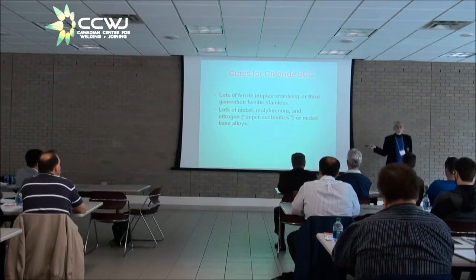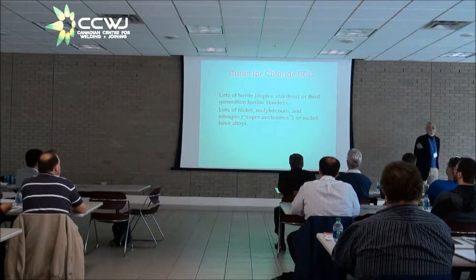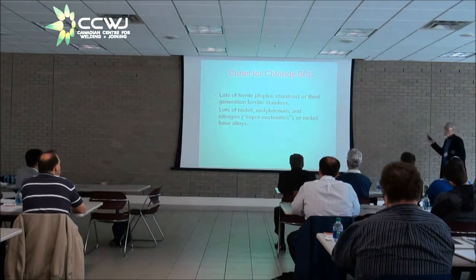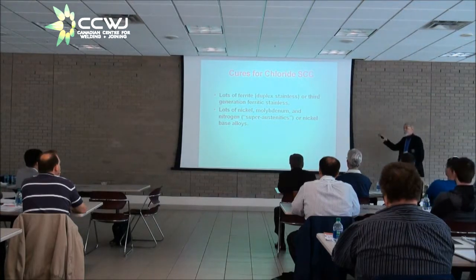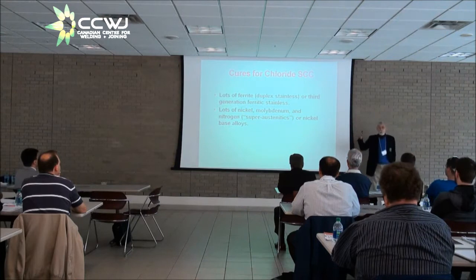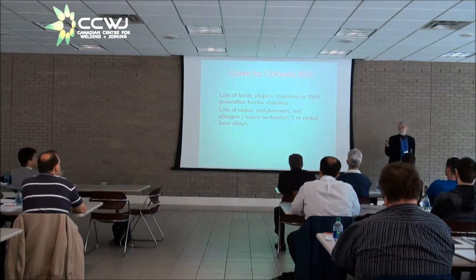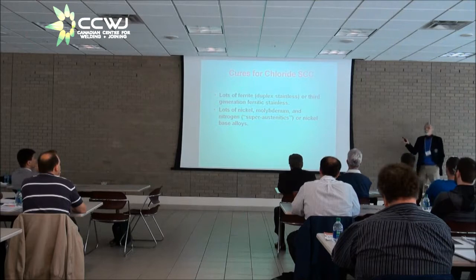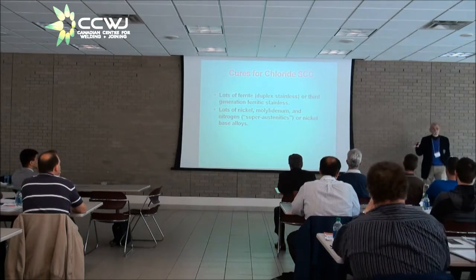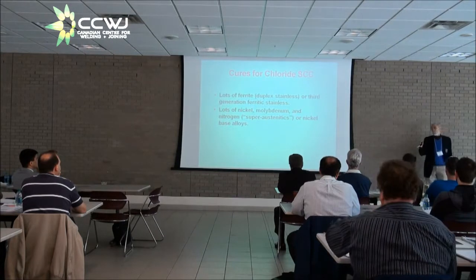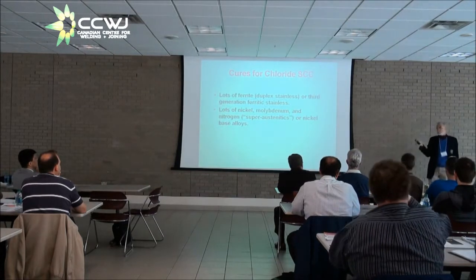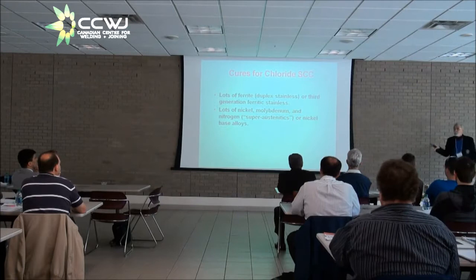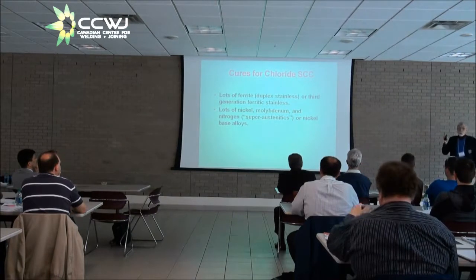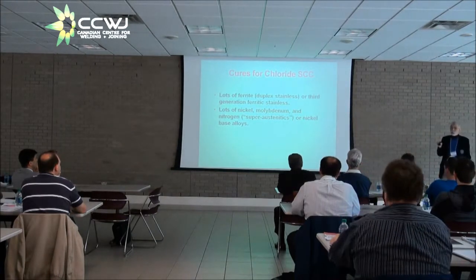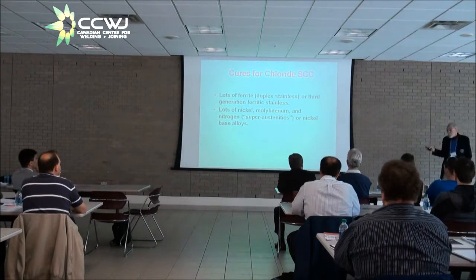Now you've got two ways to cure chloride stress corrosion cracking in stainless steel. One way is lots of ferrite. That originally led people into all kinds of advancements in what I call third generation ferritic stainless steels. These are the ferritic stainless steels like type 444, 18 chrome, 2 moly, very low carbon, very low nitrogen. Or 26-1 is another alloy, 26 chrome, 1 moly, and very low nitrogen, very low carbon. They're ugly to fabricate in any kind of thickness beyond sheet metal, so we try not to do that.